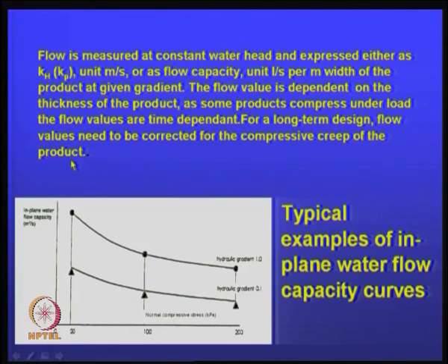This is very important, as I just mentioned, like in fact I did a couple of tests on this type of material, for a coir drain that we developed, we are looking at its in plane capacity, because in a coir drain its drainage is very important, and so we have to measure the in plane water capacity, how much water it can take under different pressures like 20 kPa, 100 kPa and 200 kPa.